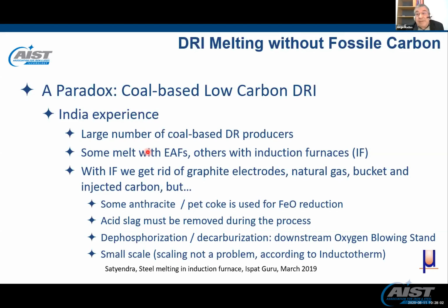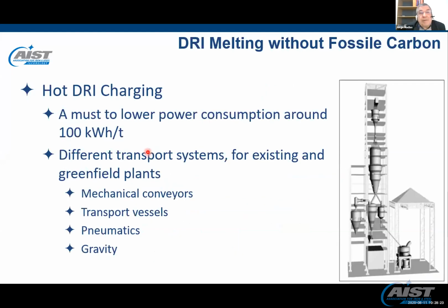And then we have the scale problem as mentioned previously by Jeremy. He mentioned 65, the largest Inductotherm furnace for steel. According to the Inductotherm guys, they say scaling should not be a problem, but I don't think that is so easy. This is a must, as Jeremy showed. On one side, we always have higher energy consumption with DRI, but then if we get rid of chemical energy, it should be even higher. So hot DRI charging should be a must for lowering power consumption, say 100 kilowatt hours per ton less than normal. So we will be in that case close to the numbers of